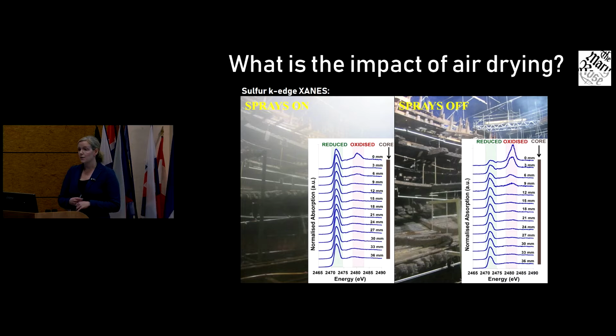So we set up a program of work at Diamond Light Source at B18 using sulfur XANES to monitor what was happening to that sulfur as we were drying it. So the pictures here show you part of the ship and show you the kind of environment when the sprays were on and then when they were off. And then what I'm showing here is the sulfur XANES. So you can see from this core sample that we've taken to the beamline, when the sprays were on, there was very little oxidized sulfur there. But then as we turn the sprays off, you get much more oxidized sulfur on the surface and it developing into the wood.